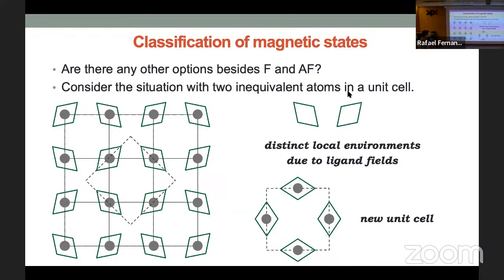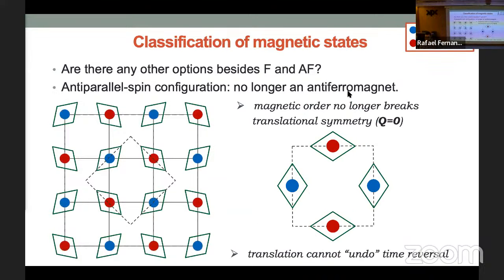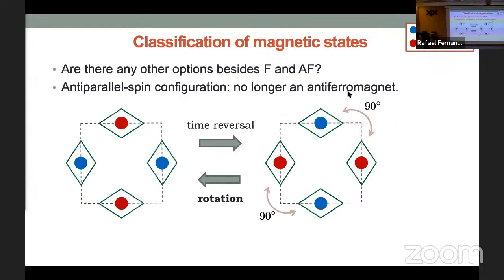So now in this case, you see my unit cell is bigger, and it has actually now two atoms per unit cell. Okay, and now I do the same kind of magnetic order that gave me antiferromagnetism. In other words, I put spin up and down in a staggered fashion. Now you see that because of these ligand fields, I do not change the size of my unit cell when I have magnetism. So it's a Q equals 0 order. So I can no longer use translation to quote unquote undo time reversal, right? But there's another thing I can do. If I apply time reversal and I follow it by a 90-degree rotation, I get back to where I started. So this is precisely what is an altermagnet, okay?